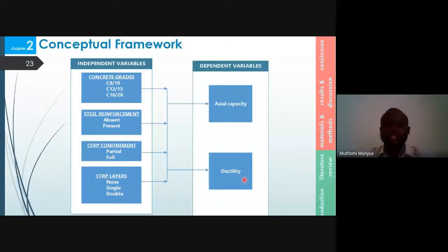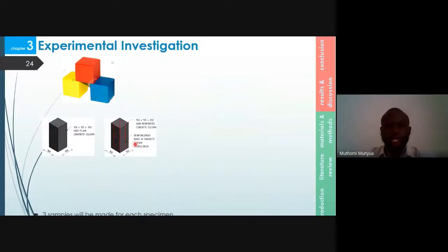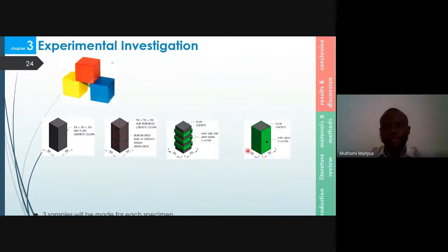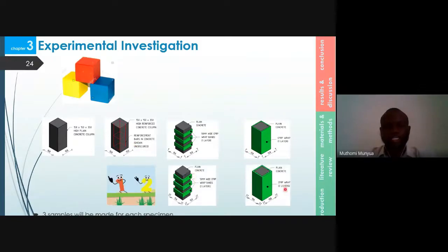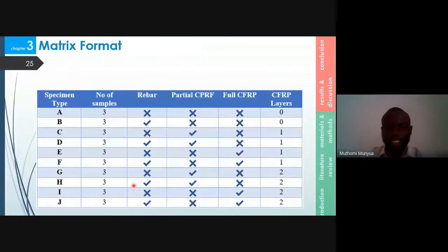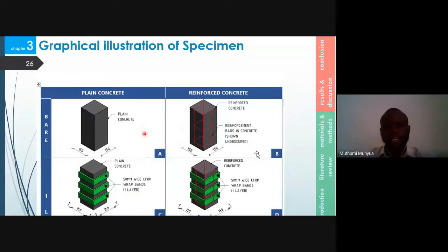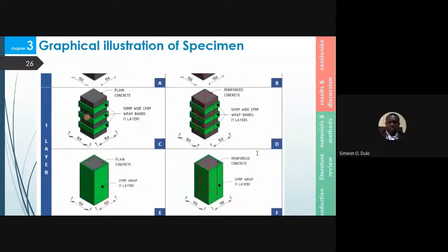The conceptual framework of the study is as shown, which guided our experiment. For the experimental methodology, we had 3 concrete grades: plain and reinforced specimens, in partial and full confinement with 1 layer, partial and full confinement with 2 layers, and to improve the credibility of our results, 3 samples were made for each specimen. This was represented in a specimen matrix as shown, and these are presented graphically. A and B were the control specimens, while C to J had either 1 layer or 2 layers.